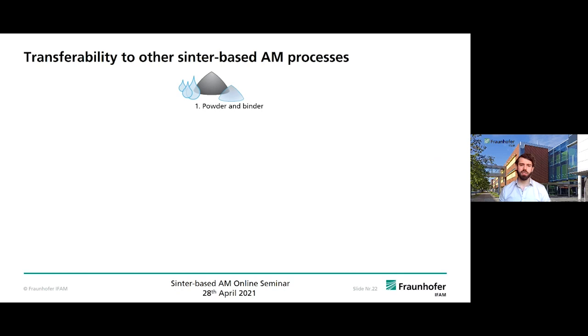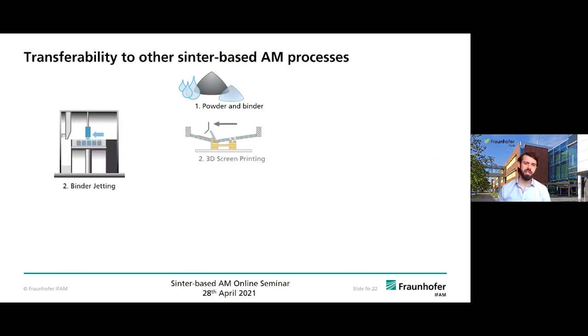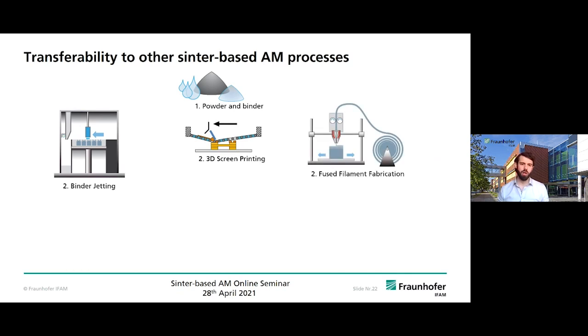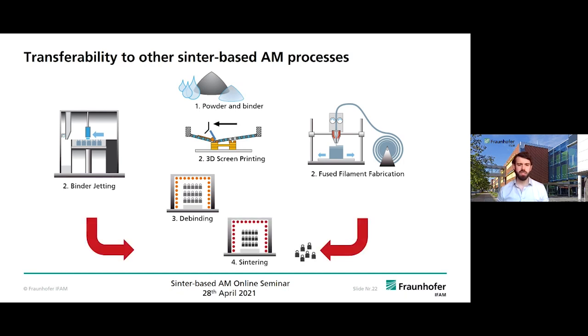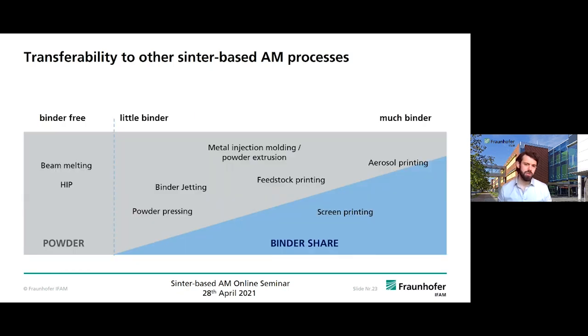So first of all, we start with powder and binder. It's not always the same powder and not the same binder, but the powder particle size distribution should be suitable for sintering, so it is in the same range, let's say. Then second comes the shaping process, and there's a difference between all sinter-based AM processes. There's a different shaping process that needs different feedstock or powder and binder properties. So in each, we have different binder or feedstock properties, we need a different debinding step, but the sintering step will mostly be the same here.